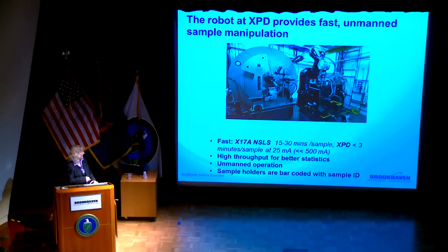To give you an example, to take this data at X17 at the NSLS took 15 to 30 minutes per sample. At XPD, it would take much less than 3 minutes, and that was at a fairly low current. When the current is higher, this time will be even less. So that's great. And of course, we're able to get the high throughput for better statistics, and also unmanned operations.